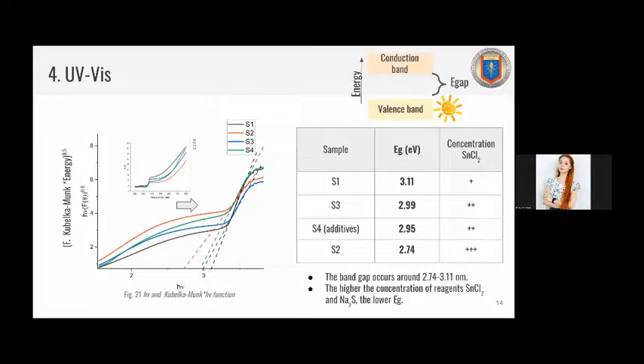So in our case, we could see that for the most concentrated sample, which was sample 2, we had 2.74 electron volts, and for the rest of the samples it was between 2.95 and 3.1 electron volts. And given that the quantum dots of tin sulfide in the literature by themselves have a band gap of 1.3 electron volts, and the anatase phase of titanium dioxide has 3.35 electron volts, it was expected that the band gap would increase with higher concentration of reagents. So it was something new that we saw, that the higher the concentration of the reagents, the lower the band gap.